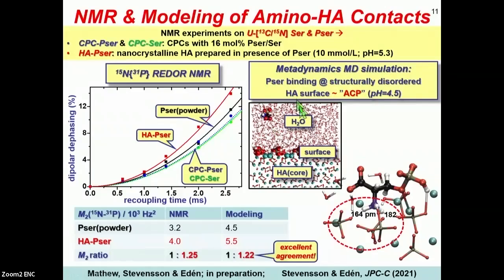We have also performed metadynamics simulations of the phosphoserine molecule in water that is in contact with a structurally disordered surface of apatite. And from these models, we calculated the nitrogen-15 phosphorus-31 dipolar second moment. You see the result here, along with that calculated from the crystal structure of phosphoserine. These results can be compared here with the REDOR NMR results. As is typically seen for this type of experiment, the experimental second moments are typically slightly lower than those you see by modeling or from a crystal structure. But here I would like to draw your attention to the excellent agreement we observe once we take the ratio between these two M2 values. You see we have a very good agreement. So this suggests that our modeling is accurate.